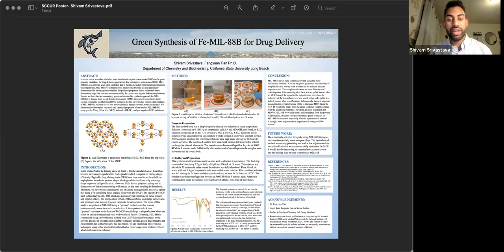So to begin in our lab, we have used two preparation procedures. The first one being a dropwise preparation and the second one being a hydrothermal preparation. The first method used two solutions. One was added dropwise into the other, and it was not yielding the best results. It was kept under stirring for 18 hours and used compounds such as terephthalic acid, iron chloride hexahydrate, water, and sodium hydroxide. After each round of centrifugation, it was found that there was no pellet formed, thus there was no MOF formed. So the dropwise preparation procedure was not the best.